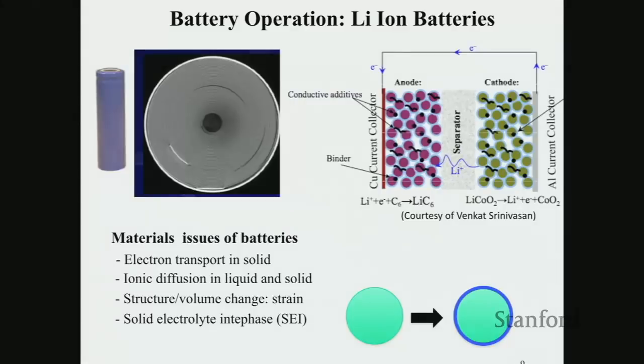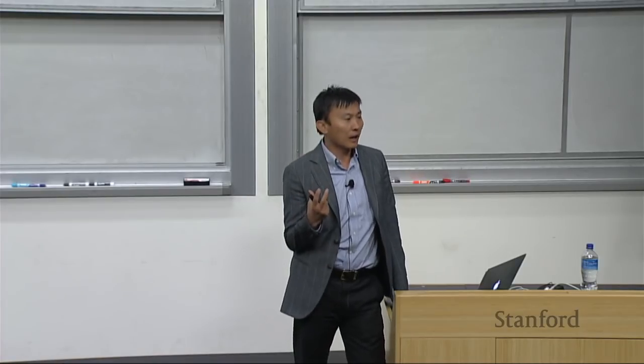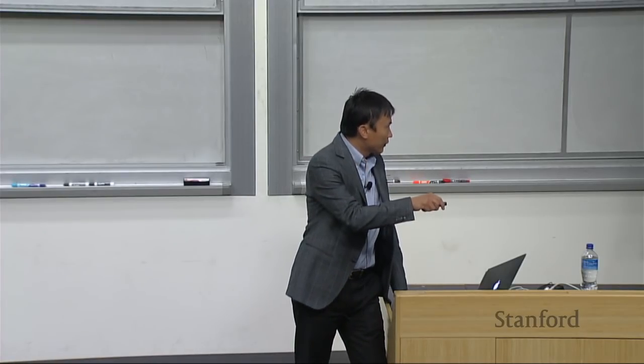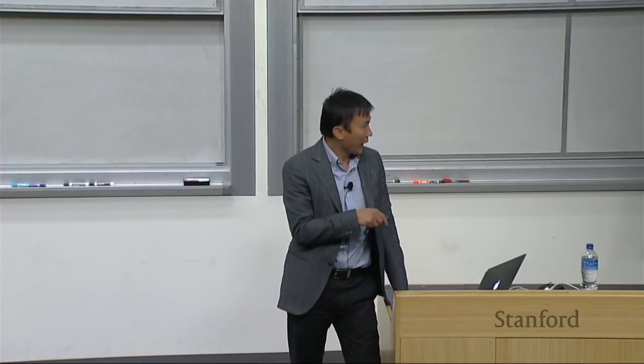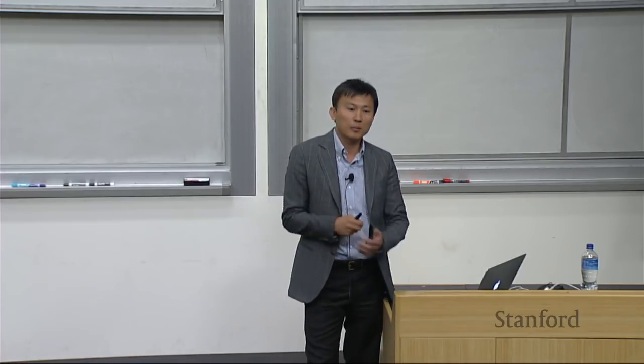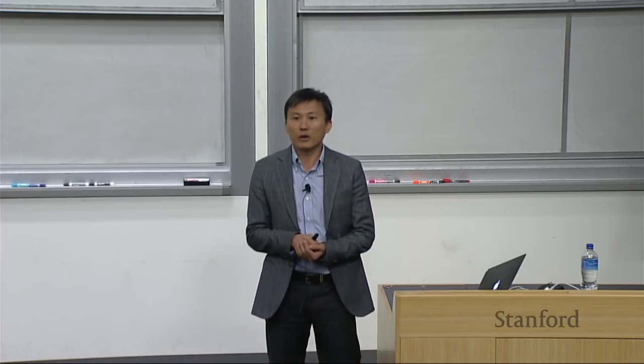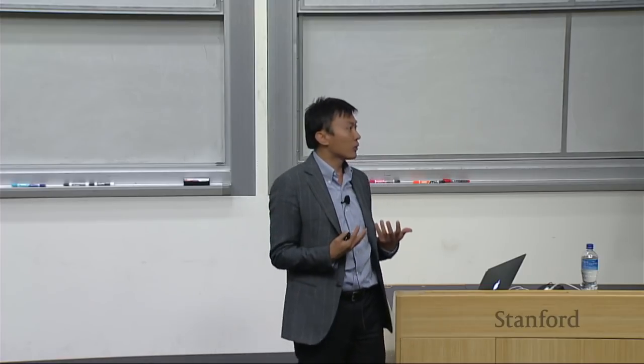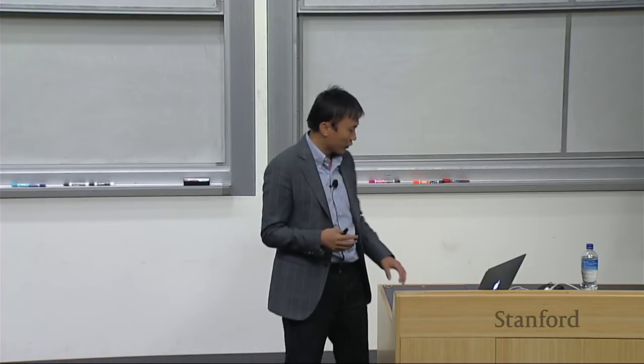And at the end, the interface: each of these particles sitting in organic electrolyte needs to be stable. The anode side particularly decomposes the organic electrolyte and generates this self-passivation layer, the so-called SEI. This needs to be stable. That allows lithium to come in and go out, but no electrons, which eventually stops the side chemical reaction.